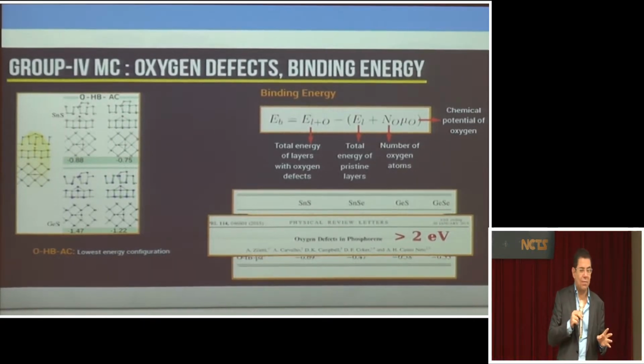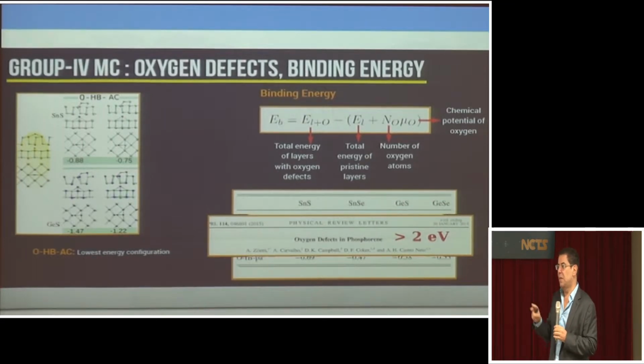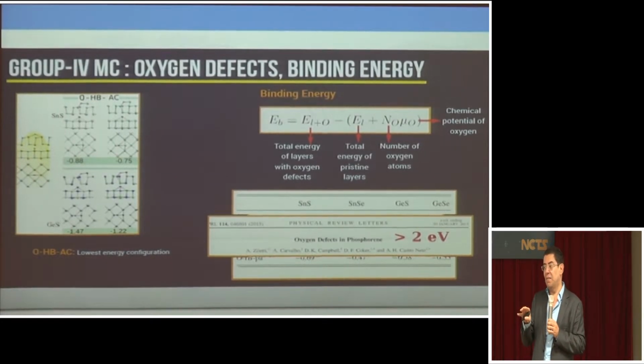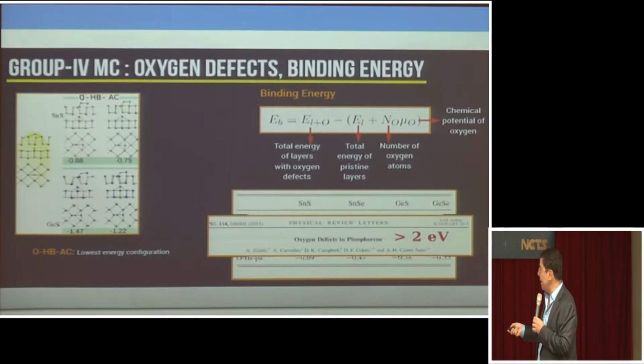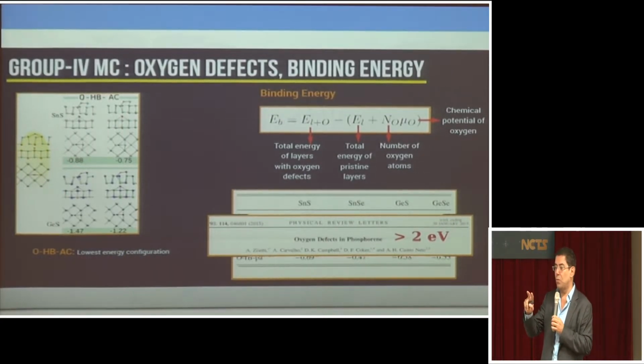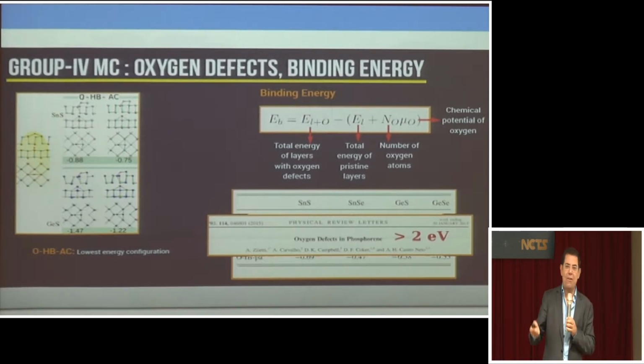As I said, oxygen is fundamental. Understanding what oxygen does here is very important. So what we found out experimentally is that black phosphorus is more unstable than, say, these monochalcogenides in regards to oxidation. Okay? And why is that? It comes from the fact that in these monochalcogenides you have two different types of atoms, and it's harder for the oxygen to bind to the structure because they have even lower symmetry than black phosphorus.